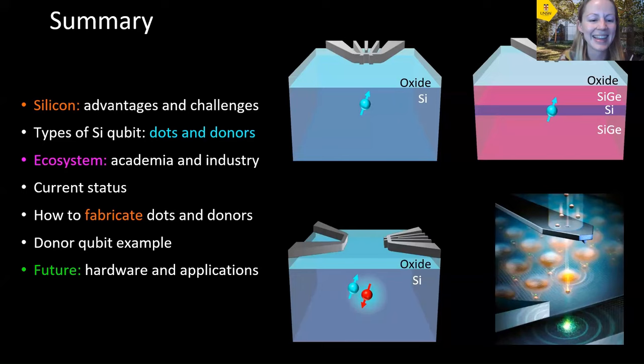Excellent, thank you. Another question was asked earlier about having the really pure silicon 28 material, and you deposited that layer. How is that purified crucible made? How can you be sure that there is no silicon 29, et cetera? That's a very good question. And the typical way that silicon 28 is produced is by using really large centrifuges that spin the silicon material. And because the isotopes have different masses, they'll be pushed towards the edges of this kind of container at different rates, and you can filter out the silicon 28. And this uses the same technology that they used when they were enriching uranium for nuclear fission reactors.